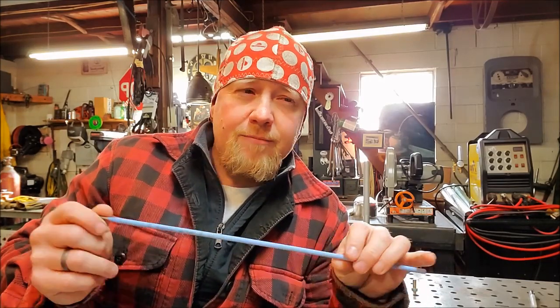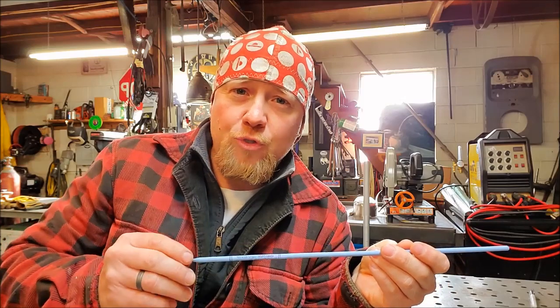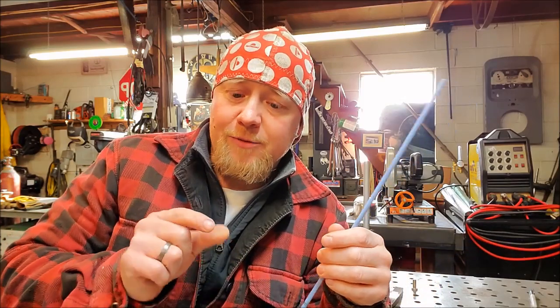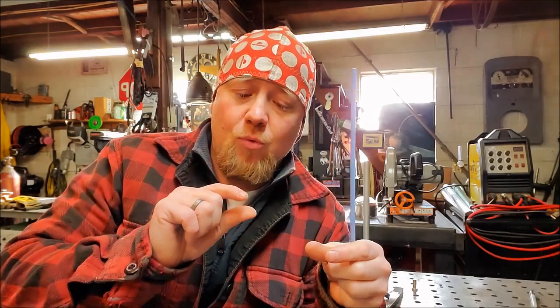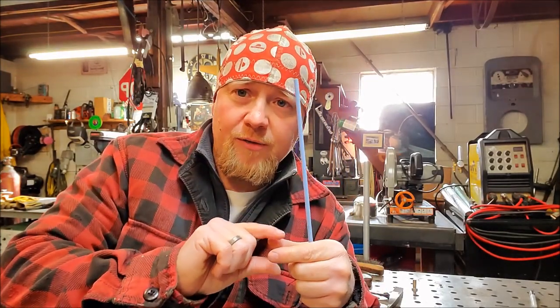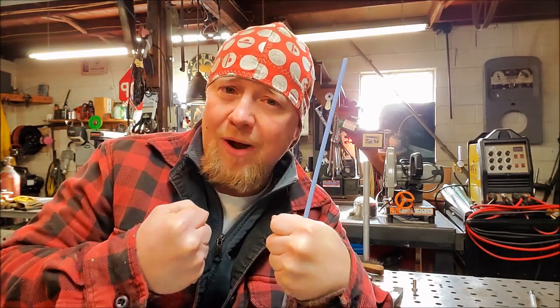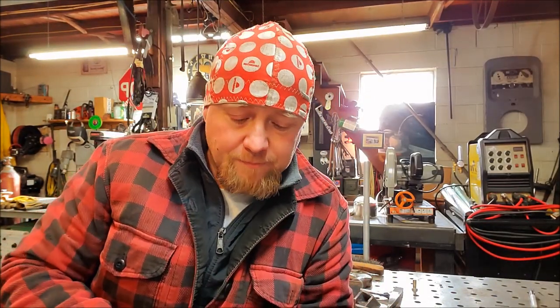They are 120,000 pounds per square inch tensile strength, which is measured exactly how it sounds. If you would weld 1 square inch of weld together and then try to pull that piece apart, it would take 120,000 pounds for that weld to pop. It would start to stretch. That stretching is called elongation. The elongation on this stuff is about 24%. So it stretches almost 1/4 of itself before it tears.